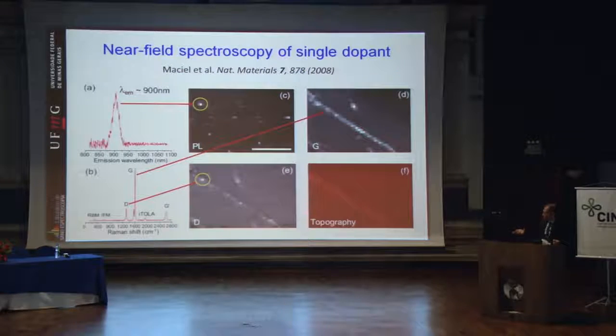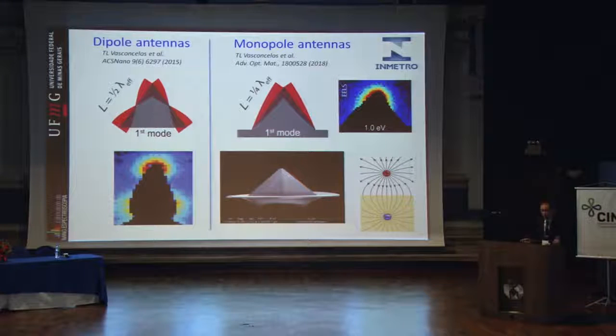And you can go to the level of, this is one nanotube, and this is one nitrogen atom doping the nanotube. And you can image the luminescence or the disorder emission of this single nanotube. And to develop this technique for Raman spectroscopy, we had to improve significantly the tips that we use to do the enhancement. The tip we have now is produced based on silicon technology. We do patterning on the silicon, and we evaporate gold, and we generate a tip that has a plasmonic resonance with the excitation laser.